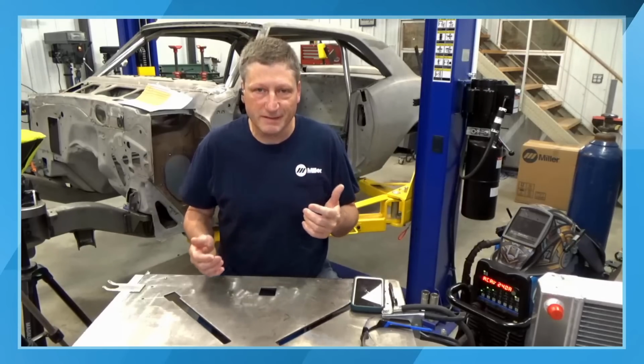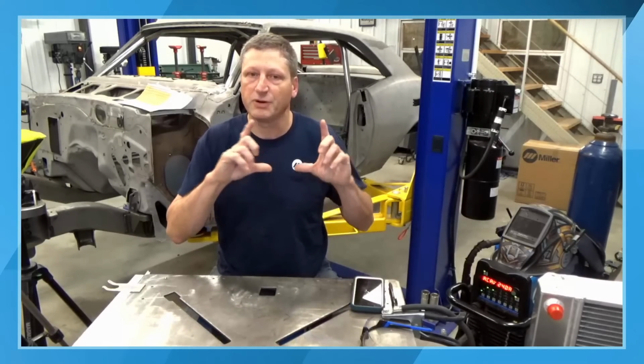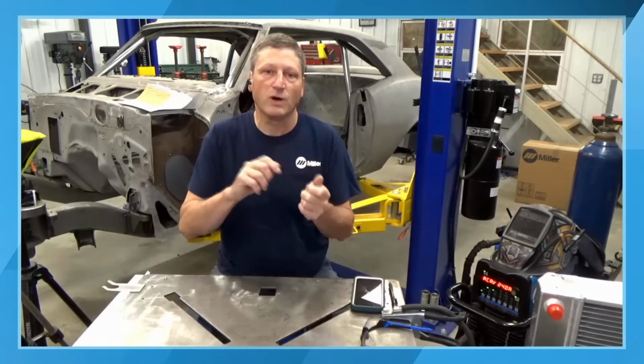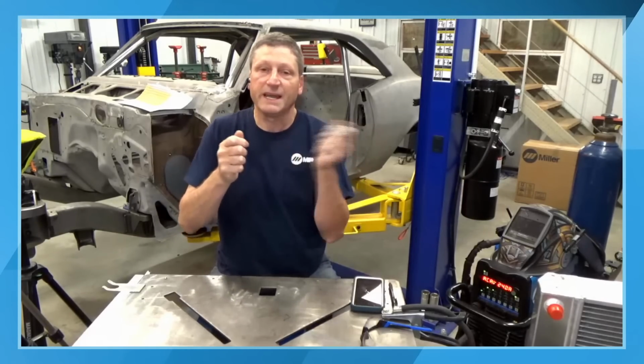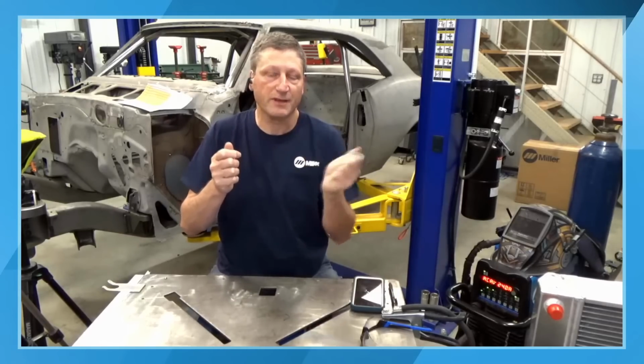We got a couple of questions here on peening the weld after welding. I think this is specifically in relation to the info earlier about post weld trying to get some of that strength back into the material. Yeah, so it helps to add strength, but it also helps reduce stress risers in the weld. So, say I kicked the rods out and windowed the side of a block and I'm putting a big patch in the side of it. I'm doing a lot of welding there, but at the same time I'm welding and then stopping and peening the weld as hard as I can, and as fast as I can, to try and get that weld puddle as it's solidifying.